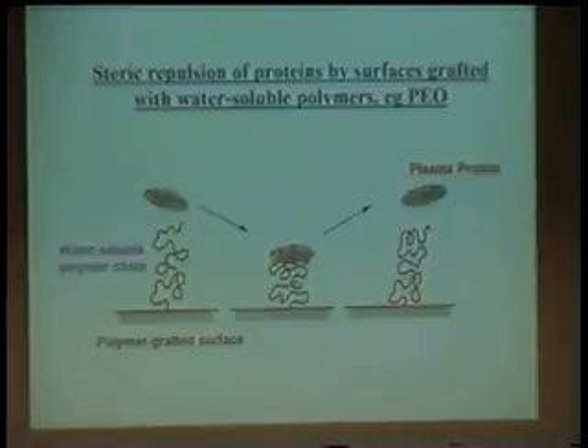The idea here is that you have the polyethylene oxide or other polymer grafted to your base surface. This is just showing one chain. You have to imagine, of course, it's a fairly dense layer of PEO or other polymer. The protein comes in. It can't get to the surface. It can't interact with the PEO itself. So it pushes down and compresses the chain, which is easily done, as I mentioned.